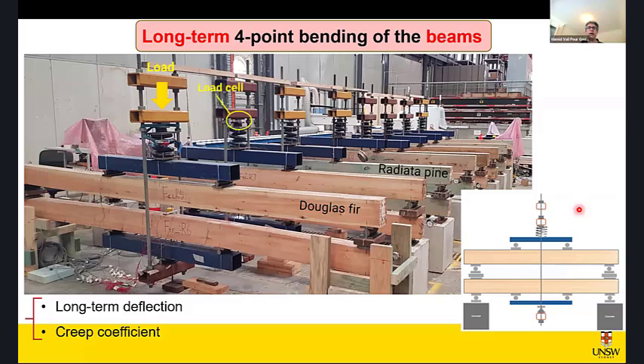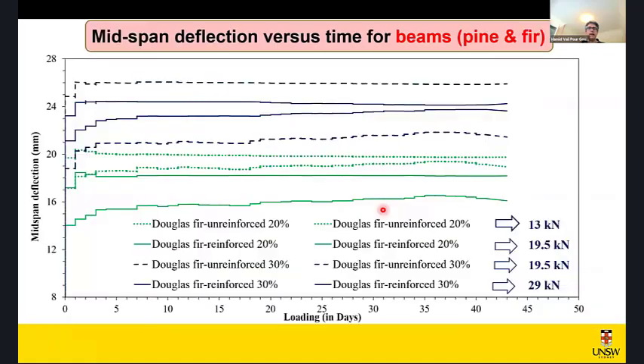This is where the loads are applied, and then the load cells and a wide range of instrumentation. You can see these cables. We have, I believe, over 120 channels to monitor different things. In addition to that, we have some mechanical gauges to measure the slip between the bars and the change in the slip and the bond between steel and timber over time. And we have both Douglas fir and radiata pine monitored.